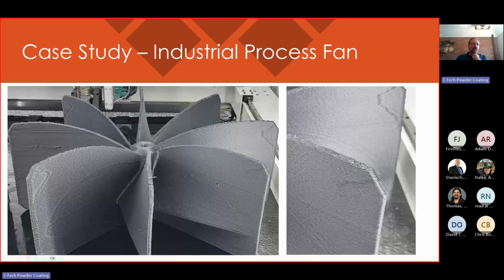And here's the first print of that model. Printed very well with good accuracy and no warp. One thing that's interesting, you can kind of see where there's a change in the perimeter layers, and they show up as these lines on the outside of the print. That could be tuned out.